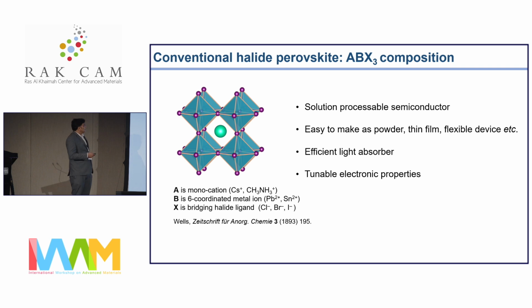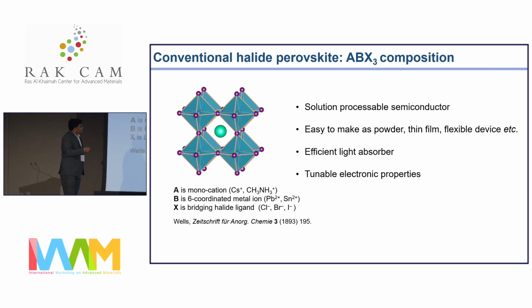So this material, as I mentioned, has flourished over the last 15 years. One of the reasons is the optoelectronic properties, but another reason is that they're very easy to make. With some amount of experience in synthesis, one can make them easily using solution processes and in various forms like powder, thin film, and flexible devices by coating on flexible substrate. And by doing this, one can tune the light absorption and the efficiency, and from there the properties can be tuned.